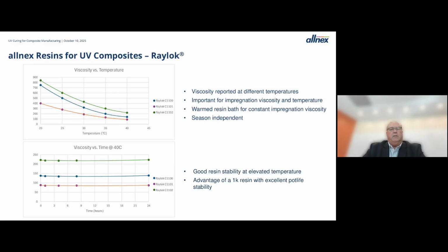And we mentioned just a couple things. One thing I haven't mentioned about UV systems is, yes, they can be very high viscosity, but that is due less to molecular weight and more to hydrogen bonding. And the nice thing about hydrogen bonding is a little bit of heat can break up hydrogen bonding and drop viscosity pretty readily. So the top graph there shows the viscosity versus temperature for the three Raylocks.